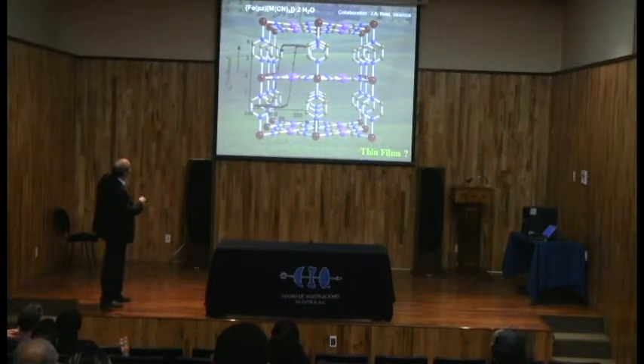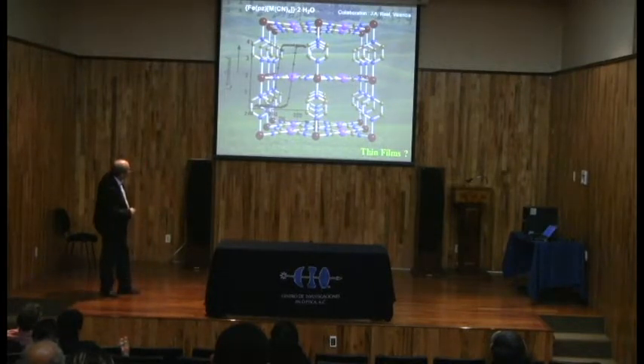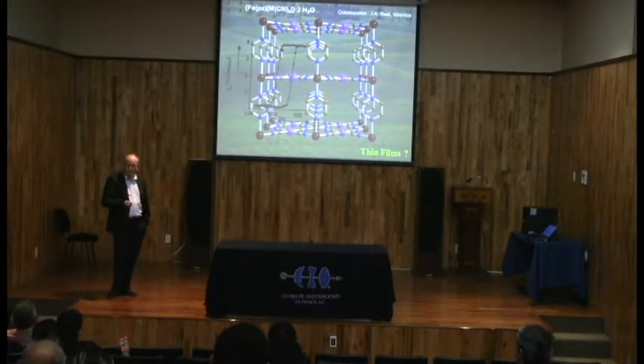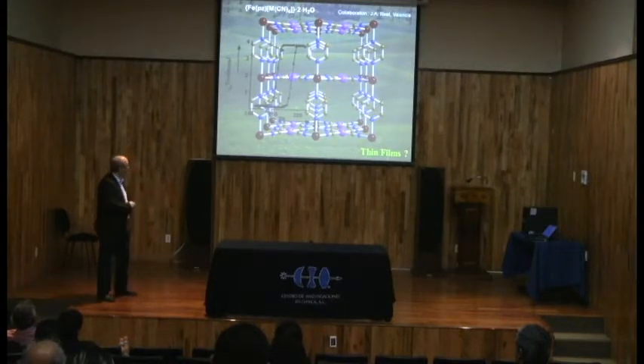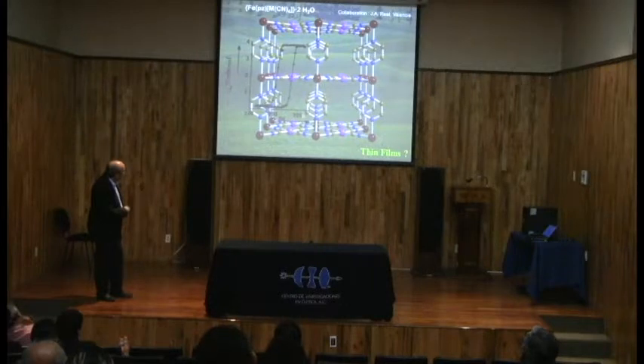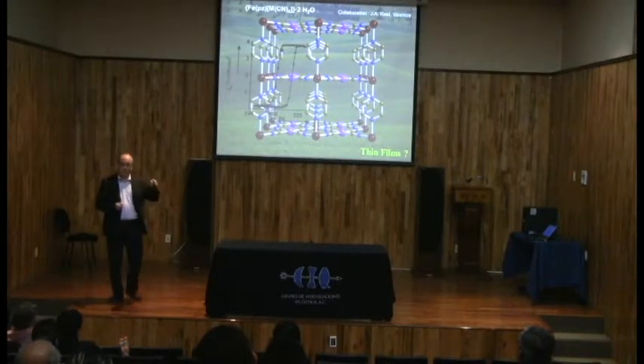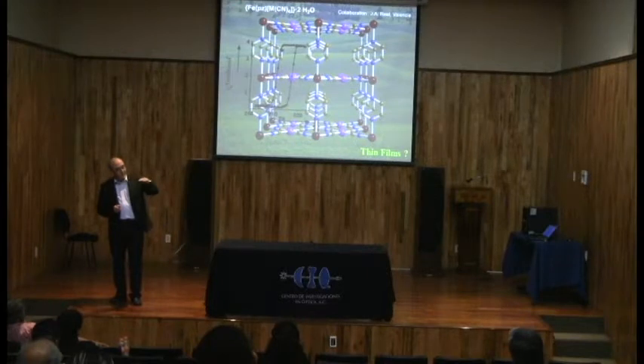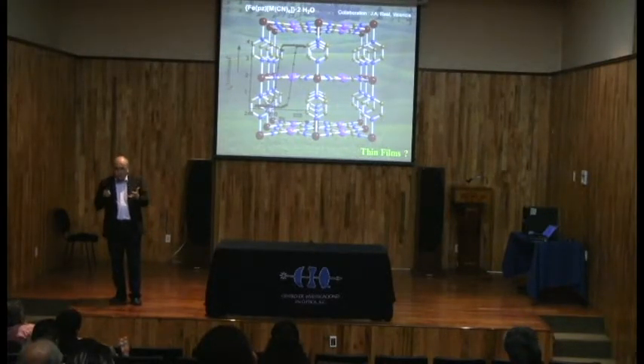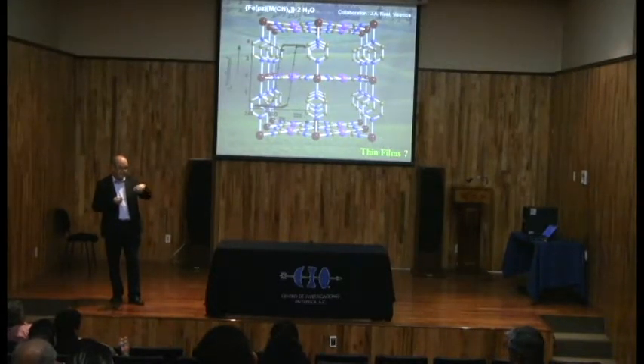Okay? So then we took this system here, the 3D polymeric coordination system here. If you look to the chi T as function of temperature, you have hysteresis. If you look to this system, you see here, you have the pyrazine connected through the iron by nitrogen. But we know in chemistry that we have another ligand, which is mercaptopyridine system, where you have exactly the same that this ring here, but instead of the nitrogen, you have sulfur. If you have sulfur, that means that you can fix it on gold surface, and you can try to make layer by layer sequential synthesis in order to construct your system sequentially by fixing the first ligand on the gold surface. So we tried to do this.